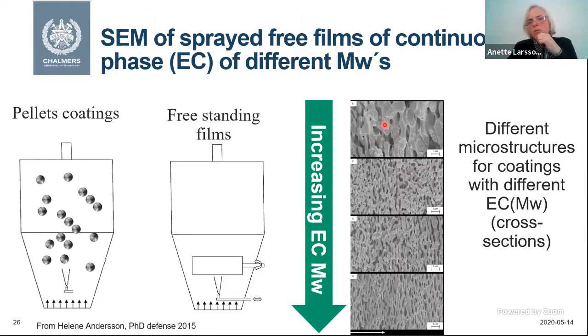And here you can see at low molecular weight, we have this. What is remaining here is the EC. So these films have been exposed to water, so the HPC has leaked out. So the holes here are where the HPC was before. So you can see that the structure and morphology is different here compared to the other ones. The pores are bigger here, and they became smaller and smaller. And that is due to the coating process, where the system was locking the phase separation, the spinodal decomposition, at different positions, which gave them different morphologies.